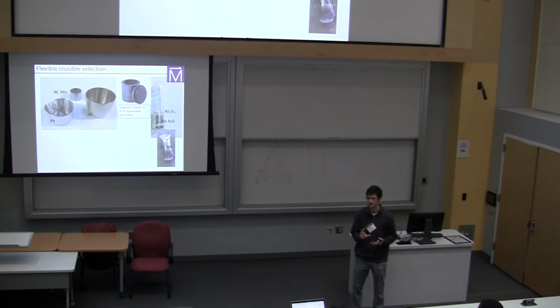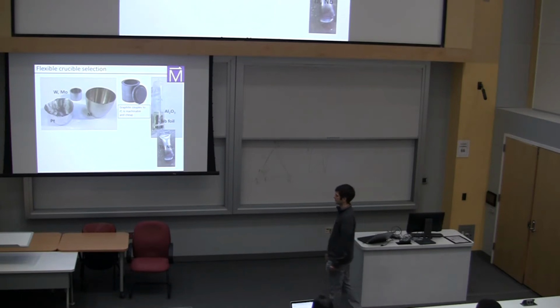A recent example is that I took some indium that had some other stuff dissolved into it up to about 1500 degrees C. By that temperature, it's over an atmosphere. I expected it to push the piston out and then have the indium vapor come spilling out. It didn't. It held it in there. I learned about this from a former postdoc from Bob Cava's group. They're doing this sort of thing as well, so I'm not just making things up. And it works incredibly well.